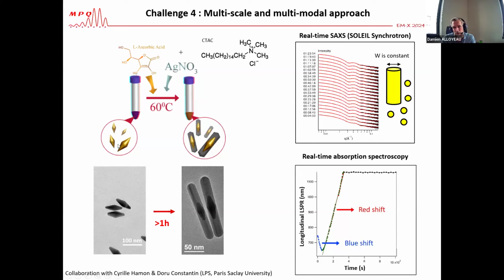First experiment, we run the growth of silver at the surface of these bipyramidal gold seeds. Very simple growth process. You have the bipyramidal gold seeds, you add the silver precursor, the ascorbic acid, and the CTAC. Here is what you get when you follow this simple reaction by SAXS. What those curves tell you is that you have the growth of anisotropic objects with a constant width. And if you want to have a perfect fit on your SAXS curve, you need also to add in your model a lot of small spherical silver nanoparticles that grow together with the nanorods.